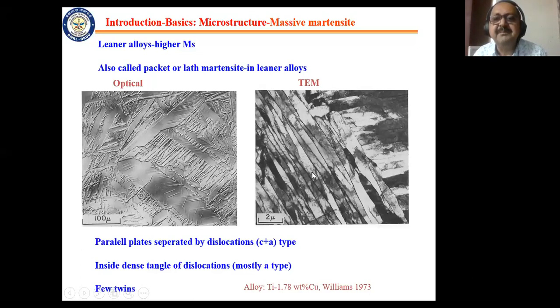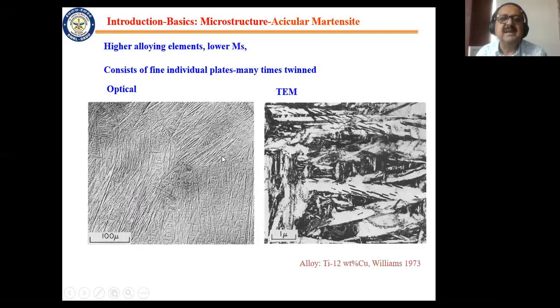Again, TEM picture, and this has got very little twinning in it, and a lot of dislocation structure which you can see inside. Then in the alloys which are much richer, similar alloy, not the same alloy, where you have now increased the copper percentage to 12.8%. Here you see the structure of the martensite is slightly different. It is again very fine lath, but now you can see a lot of twins inside, if you do TEM. So this is called acicular martensite, and this occurs in much richer alloys where the MS temperature is comparatively lower as compared to the other example that I showed you.